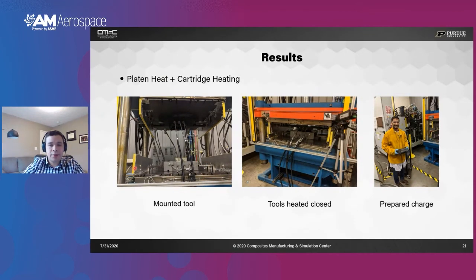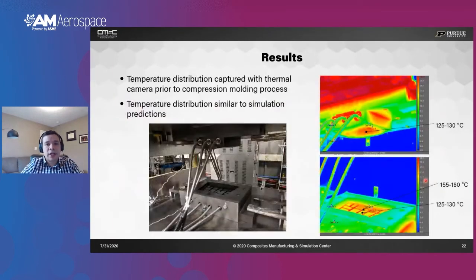So we can see here on the right, the tool mounted on the hot press. In the middle, we can see the tool being closed inside the hot press, and a thermal camera that we use for monitoring the temperature at the upper and lower sides of the tool. And then here, the molding charge being ready to be dropped in the mold.